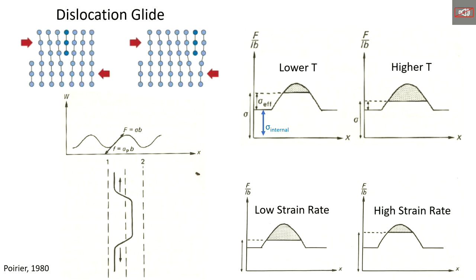And you want to think of there being a diagram of the amount of work required to get the dislocation to move one lattice dimension. And that, at low temperature, requires enormous application of stress. But the higher the temperature you go, the lower that stress becomes because of the thermal vibrations. So there's an energy barrier that you have to overcome, and the higher the temperature, you get rid of more and more of that energy barrier. So the stress that you need to apply drops when you increase temperature.